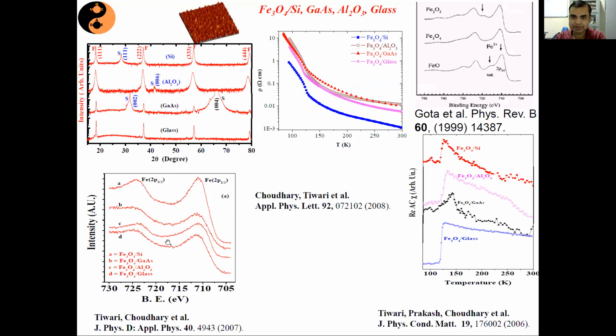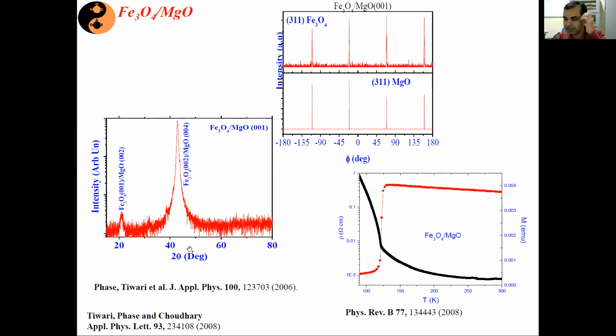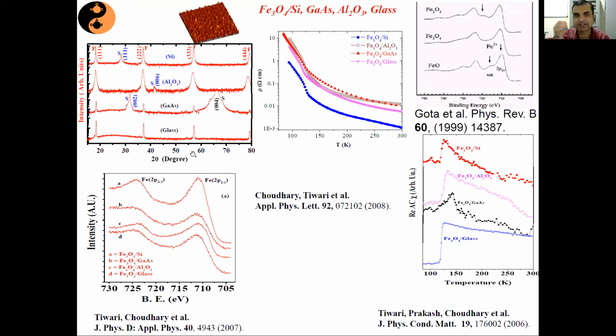Now, this was all about the MgO substrate. If I picked the MgO with C-axis orientation, the film was also growing C-axis oriented, and it was epitaxial in nature. Now, what happens when I pick some other substrate like gallium arsenide, silicon or Al2O3? If you look at these results, what do you see? On all these substrates, the film is growing along the 1-1-1 direction. So in the normal X-ray diffraction pattern, we get only 1-1-1, 2-2-2, 3-3-3 reflections. We do not get the 0-0-1 kind of reflection which was available in MgO. Why does it happen? And surprisingly, even on glass, which is an amorphous substrate, you can see only the 1-1-1 peak. What information do we get from here?